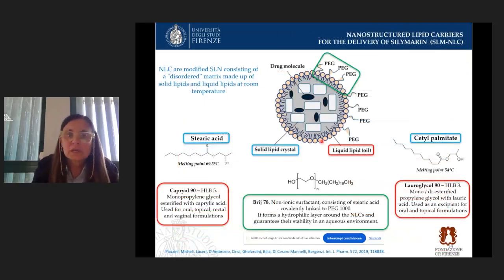Here, a study related to the delivery of silymarin by using nanostructured lipid carriers. In this case, we prepared two different NLC. One NLC contains silymarin and stearic acid as solid lipid, Capryol 90 as liquid lipid, and Brij 78 as a non-ionic surfactant.